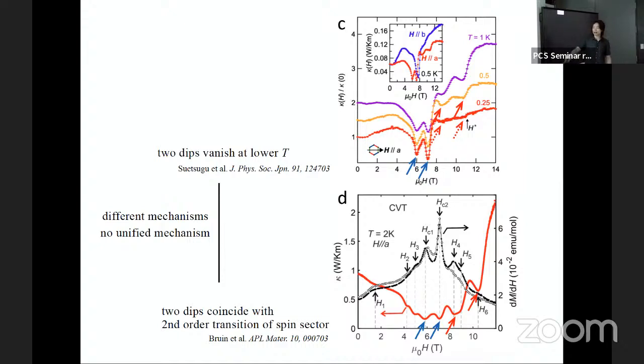But there are two other dips that do not seem to coincide with any phase transition. However, these two other dips also have some interesting new data. That is, if you go to even lower temperature, 0.25 Kelvin, it seems like they start to go away. This suggests that these two dips and those two dips come from different mechanisms.